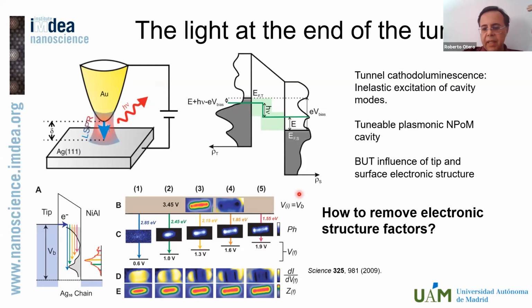It is also known, at the very least since 2010, more or less, that the electronic properties of tip and sample are very important. You can see that in this simple sketch, right? If you apply a bias voltage between the tip and the sample, you shift the Fermi levels of tip and samples. Therefore, you shift the electronic density of states of tip and sample, and therefore you change the availability of initial and final states for the inelastic tunneling process. So at the end of the day, what you get is a convolution, if you like, of purely optical and electronic properties. So what we would like to find out is a method to eliminate all these electronic contributions and be left completely with the optical characterization of the cavity.